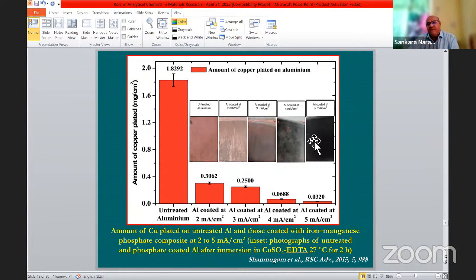When we go for a very high current density coating, 5 milliampere, the surface is completely covered by the phosphate coating, and the amount of copper deposition is only 0.03 milligram per centimeter square. So you can use this very simple chemical analytical method to estimate the porosity of coatings.